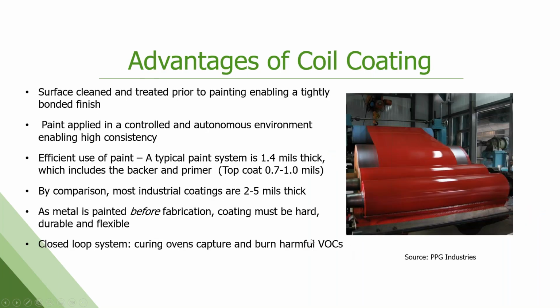Because of this size and how fast this runs, there's a lot of advantages to this process, right? We're cleaning the surface and treating it prior to the paint being applied. It's a very controlled environment, so we have great reproducibility, not only in our film thickness, but in our color control, which is very important in the architectural space. If I run colonial red today and I run it 2 weeks from now, it's going to look exactly the same in color and appearance.